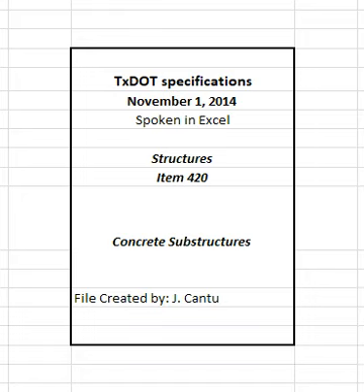Remove inside forms, walls and top slabs, for box culverts and sewers after concrete has attained a compressive strength of 1,800 psi if an approved overhead support system was used to transfer the weight of the top slab to the walls of the box culvert or sewer before removal of the support provided by the forms. Forms or parts of forms may be removed only if constructed to permit removal without disturbing forms or falsework required to be left in place for a longer period on other portions of the structure.